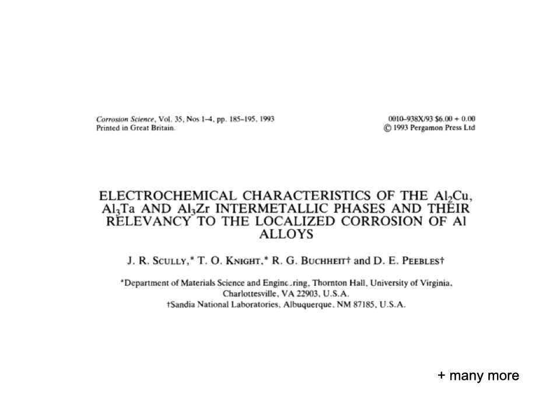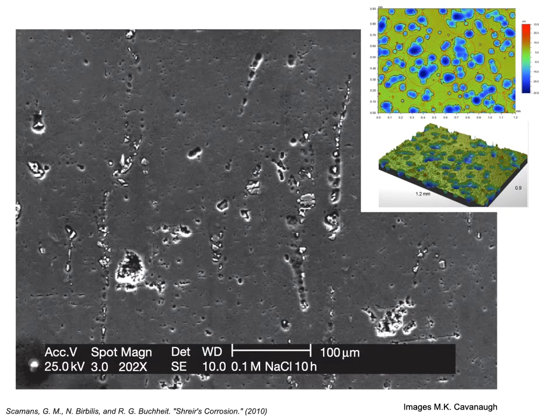Indeed, throughout the 90s, traction also emerged for the so-called deconstruction approach of understanding corrosion of complex alloys, such as high-strength aluminium alloys, by understanding the electrochemistry of their many phases. And this has become somewhat of a gold standard now, giving rise to a field known as corrosion metallurgy. This is an example of pitting on aluminium alloy 7075-T6, where we see a morphology of corrosion that we now know is deterministic and quantifiable in terms of morphology and evolution, allowing things such as structural integrity prognosis to emerge.